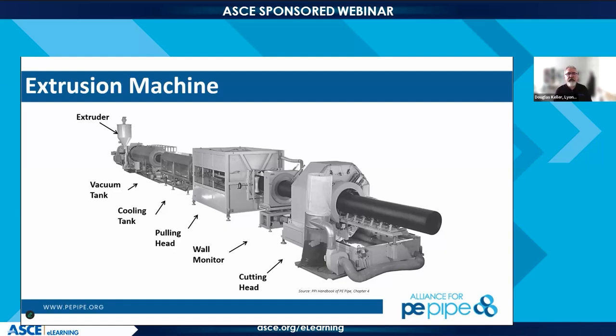This is kind of an old schematic of a polyethylene pipe production line, but way on the left, in the upper left corner, you see the extruder. It's somewhat hidden. In that extruder, we have a single screw that is turning. It is using frictional heat to take those pellets, melt them, and form them into a stream of material coming out of the die. That then goes into the vacuum tank where it is sized. Most polyethylene is sized to the outer diameter of the pipe. So we have a certain fixed outer diameter that we're looking at. And then we can adjust by changing the die setup how thick the pipe is and what the diameter of the pipe is.